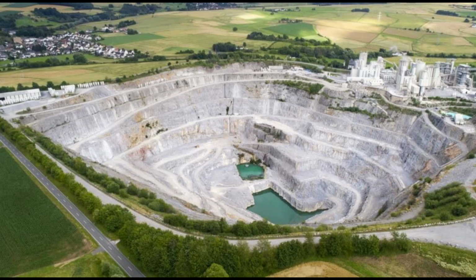Concrete can be carbonated by two main methods, weathering carbonation and early age carbonation. However, as early age carbonation methods have gained recognition due to their substantial carbon sequestration proficiencies, some authors have argued that the effect of early age carbonation curing may succumb to weathering carbonation later on. For example, a 2020 article writes, "Experimental results suggest that early age carbonated concretes with high water-to-cement ratios, greater than 0.65, are more likely to be affected by weathering carbonation."